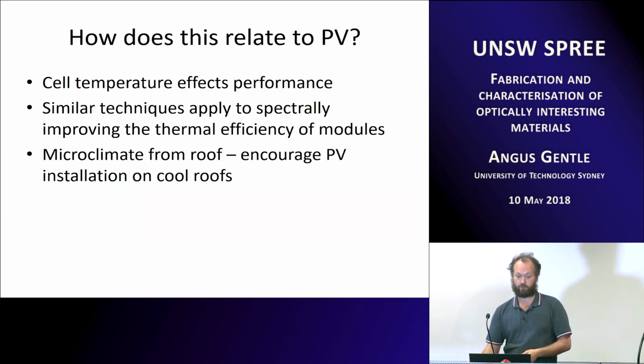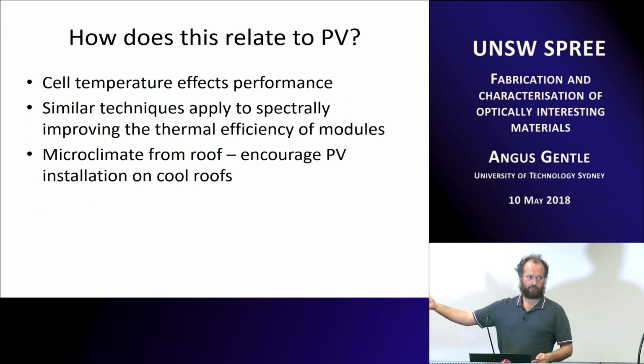So I sort of said, how does that relate to solar cells? Basically, cell temperature affects the performance of your cells. If you look at encouraging people to put them on white roofs as much as possible, that's what you want to do. And all the techniques we're using for this different spectral control, you can do the same thing on modules. Up until quite recently, most people doing silicon cells would say, yep, we measure up to 1300 nanometers. Past that, who cares? It doesn't get used at all. So measure across the full wavelength spectrum, from UV out to 25 or 50 microns, measure the whole thing, do proper thermal modelling, and see where you can actually fix things up.